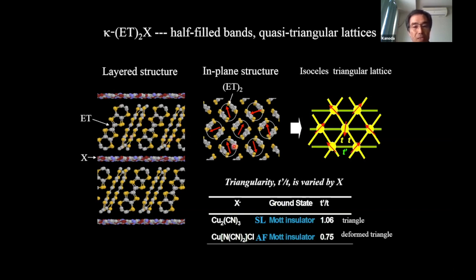And this is the in-plane structure. This ET forms a dimer. This dimer forms an anisotropic triangular lattice, so an isosceles triangular lattice. And this lattice is simply modeled as this anisotropic triangular lattice, characterized by two kinds of transfer integrals, t and t prime. By changing anion X, we have several materials with different anisotropy, t prime over t.